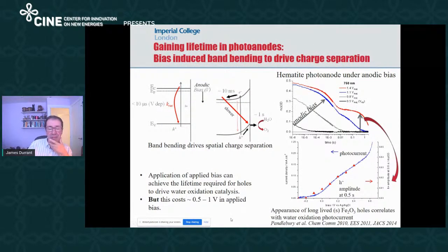Now, how do we gain lifetime? By far the easiest way to gain lifetime is to introduce band bending. If you apply a positive potential, then you generate a space charge layer, just as in the PN junction of a silicon solar cell. And that space charge layer has fields which drive holes to the surface and electrons to the bulk.